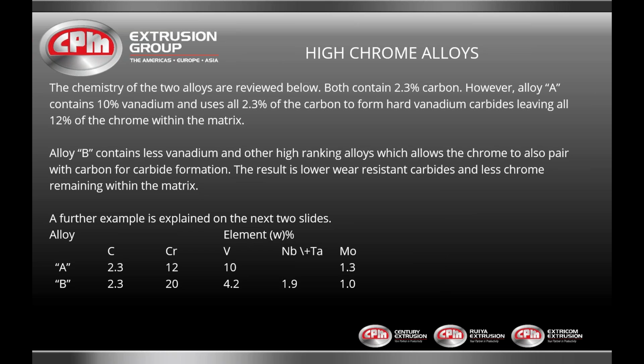In the high chrome alloys, the chemistry of the two alloys reviewed below both contain 2.3% carbon. Alloy A contains 10% vanadium and uses all 2.3% of the carbon to form hard vanadium carbides, leaving all 12% of the chrome within the matrix.